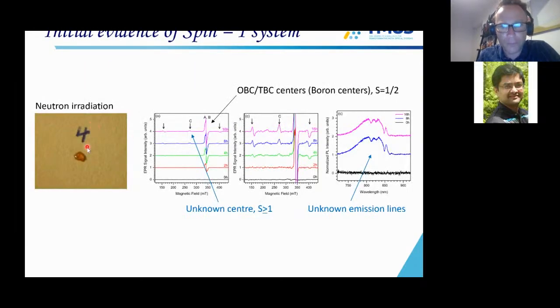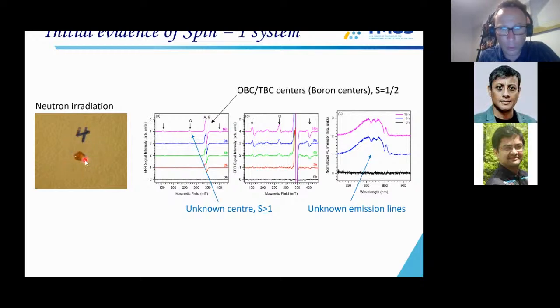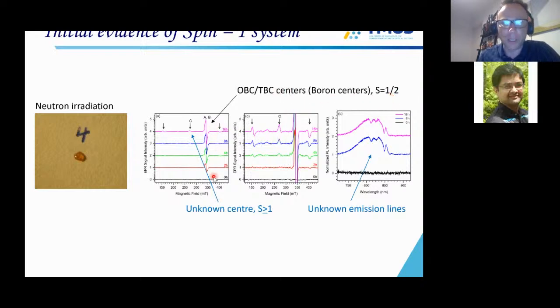Initially, we had a collaboration with a group in Brazil on what happens when you irradiate hBN with neutrons. You get these beautiful pink crystals. This is actually a pink crystal. It's not a false color image. They actually become pink. And this research was done basically in the 70s. People irradiated with neutrons, and they saw these OBC and TBC centers with spin half. You can open any literature on hBN from the 1970s, and you will see these beautiful lines.